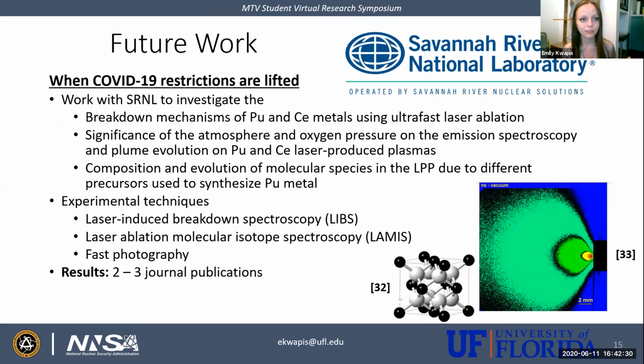So just to wrap up this section, with relation to LIBS spectra, I expect cerium spectra to be more reactive than that of uranium, and plutonium to be more reactive than that of cerium. So starting to wrap up this presentation, as soon as I can get to Savannah River National Laboratory, I'll be performing laser-induced breakdown spectroscopy on plutonium and cerium metals, where I'll be focused on, once again, actinide plasma chemistry, looking at the oxidation effects in the plasma plume, and its effect on the emission spectra and the evolution of the plume itself.